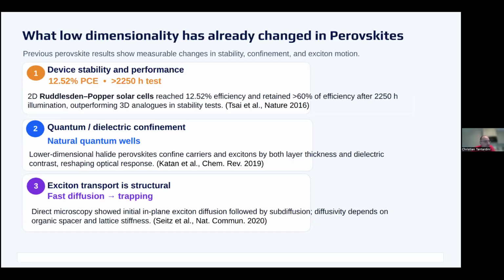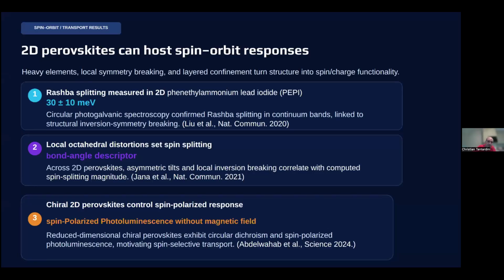The same is true when we have 2D perovskites: we see that they are natural quantum wells. Specifically, when we have these inorganic and organic layers, they change the electronic properties and specifically allow or not the excitons to be transferred. And the same is true when we look, for example, at exciton diffusion: they can also be trapped, okay? And the trapping of the exciton can be released by diffusion or subdiffusion.